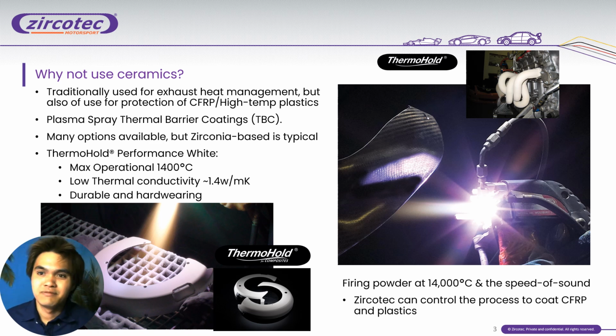The plasma spray we use is a thermal barrier coating that is zirconia based, called Performance White. Performance White has a low thermal conductivity of 1.4 watts per meter Kelvin and a maximum temperature of 1400 degrees. These properties are great because we are using this for carbon fiber wheels and brake parts, and they allow the operational temperature of these parts to be increased.